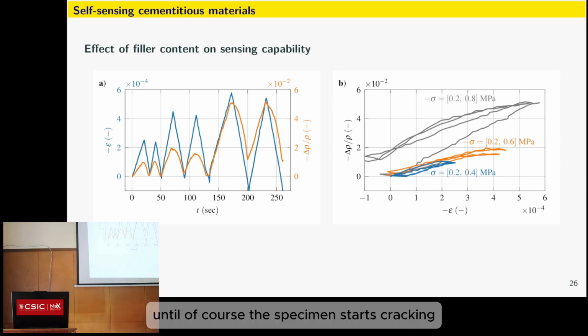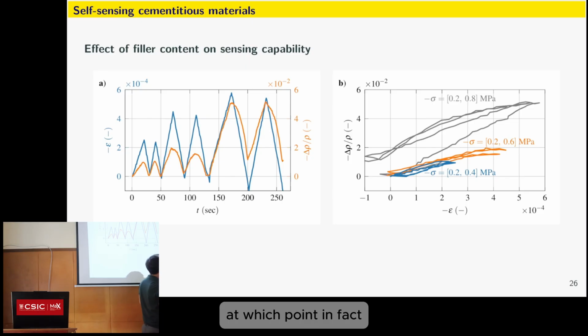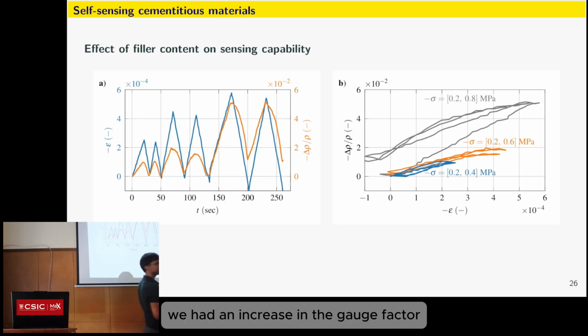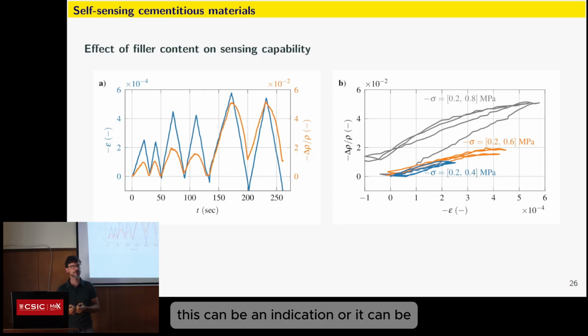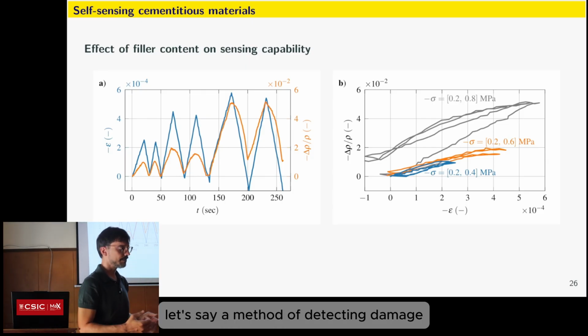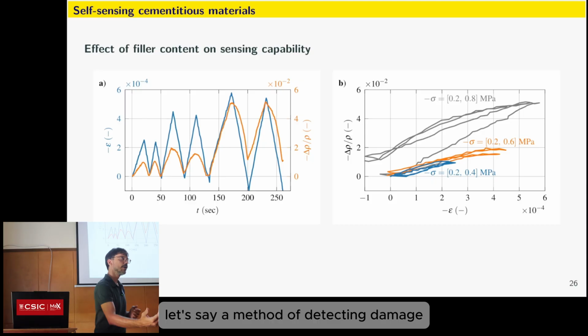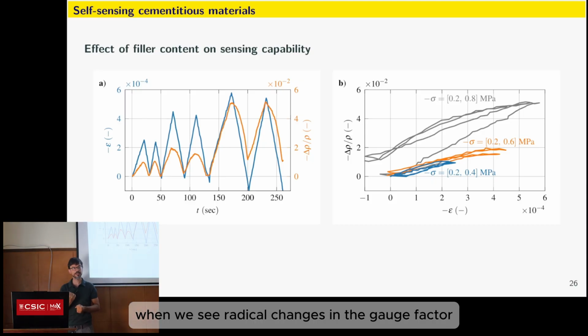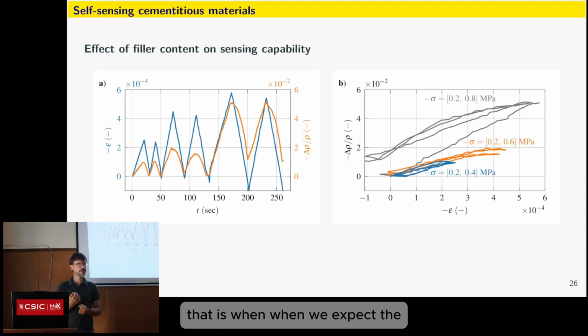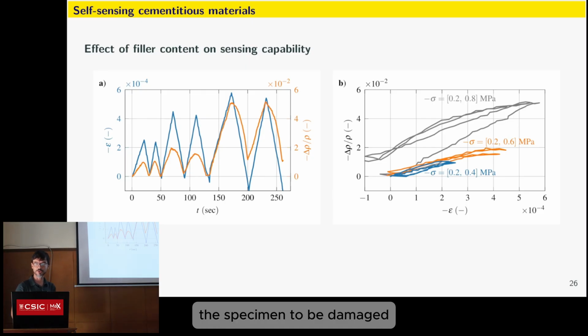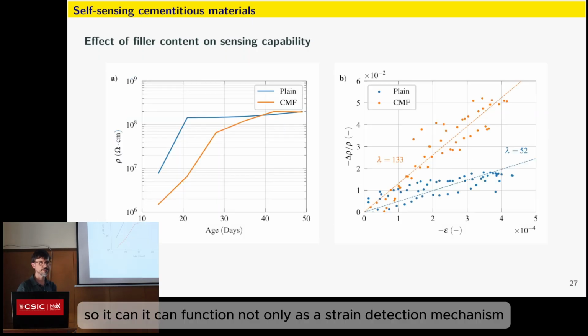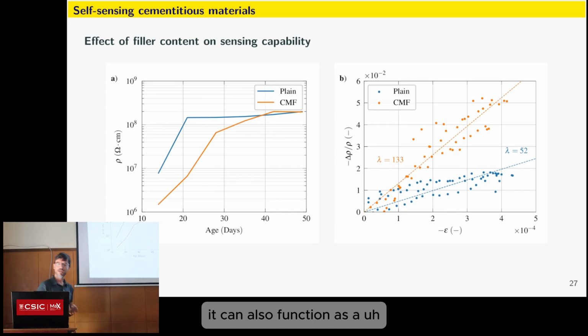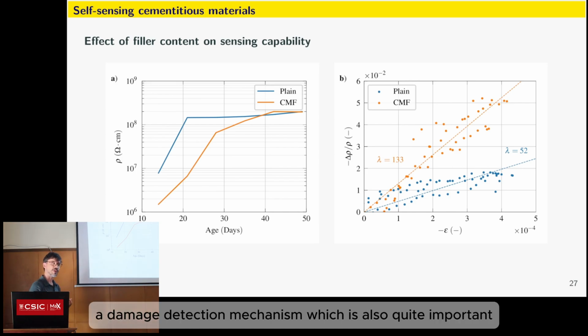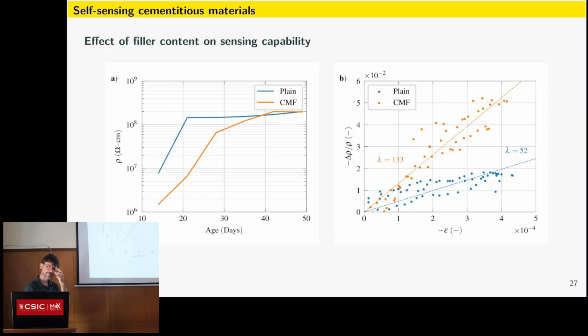until, of course, the specimen starts cracking, at which point, in fact, we had an increase in the gauge factor. This can be an indication, or it can be, let's say, a method of detecting damage. When we see radical changes in the gauge factor, that is when we expect the specimen to be damaged. So it can function not only as a strain detection mechanism, it can also function as a damage detection mechanism, which is also quite important.